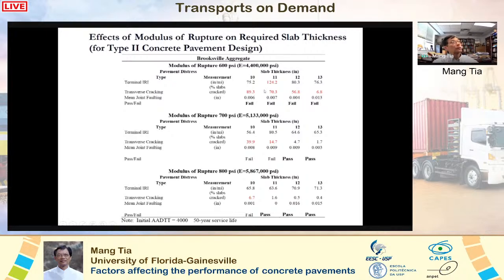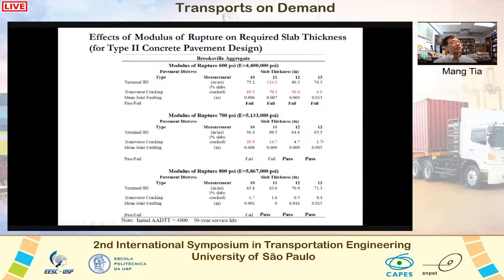When the flexural strength is 600 psi, they all fail. When we see a red number here, it means it failed. All of them fail for a thickness of 13 inches. But if we increase the flexural strength to 700 psi, then we only need 12 inches, and it would last for 50 years. If we go up to 800 psi, we only need 11 inches. So let me repeat this: if you use the same concrete made with the same aggregate and increase the flexural strength, the performance would be better.